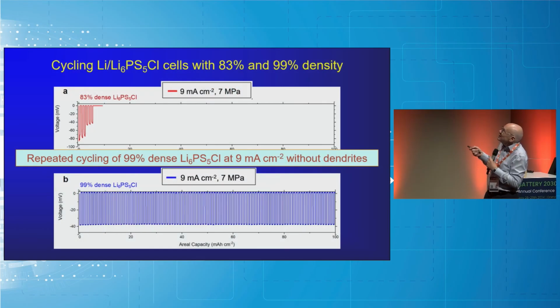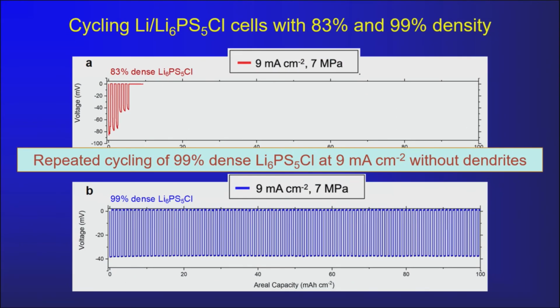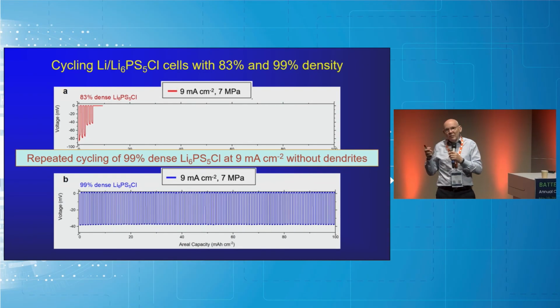And these are two cells, identical cells, cycled. The only difference is this is 83% dense solid electrolyte. This is 99% argyrodite. Same current density. This one fails quickly. We stopped after 100 cycles because it was getting rather boring watching this at 9 milliamps per square centimeter. So there is an important correlation between microstructure and this big problem that's always faced this field of mitigating dendrites to make lithium metal anodes practical. Now, there are still lots of other problems to solve, but it's an intriguing correlation that may help us in the future. So I want to end at this point.